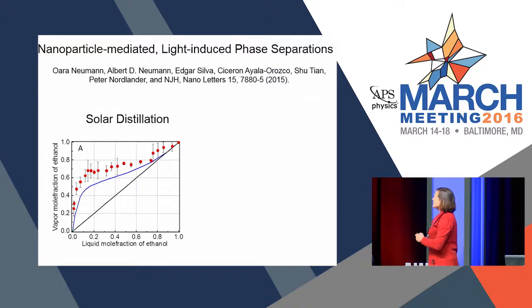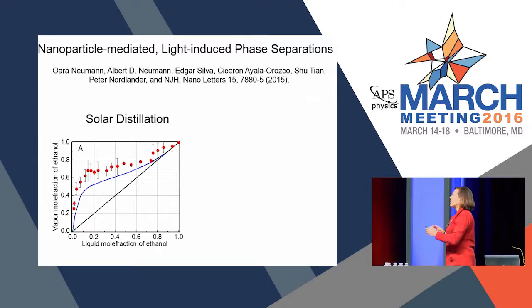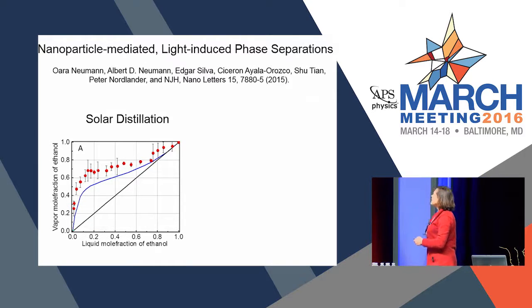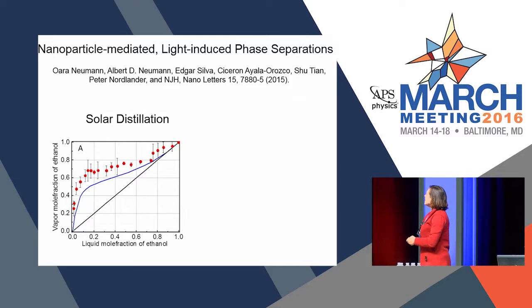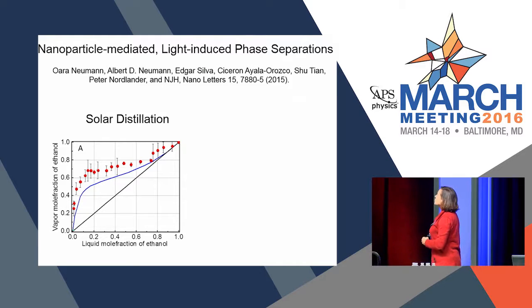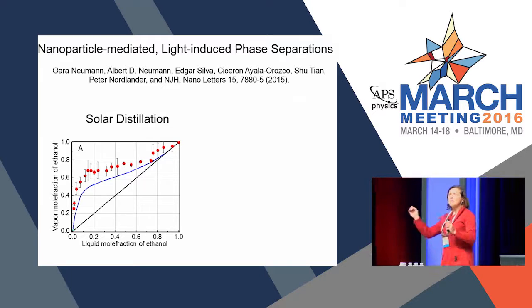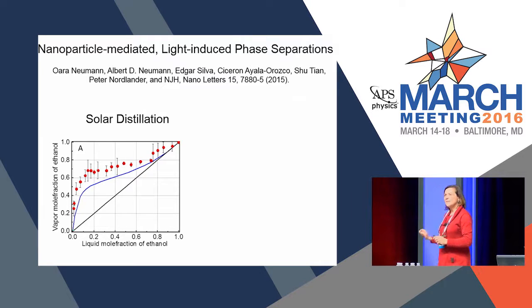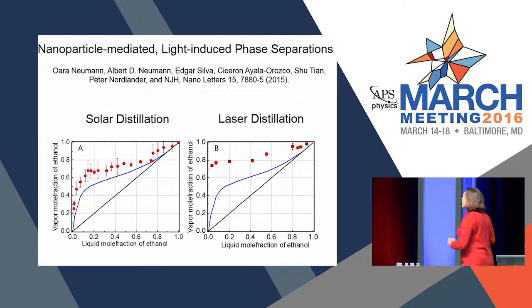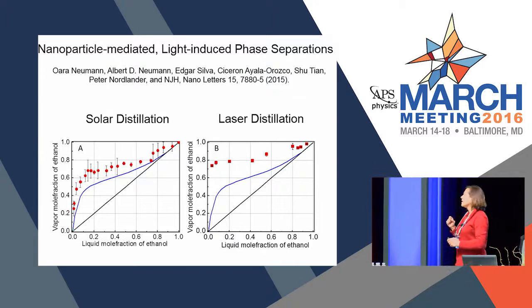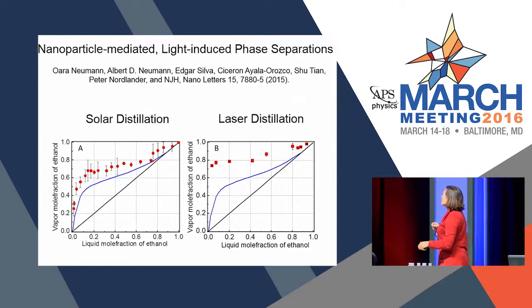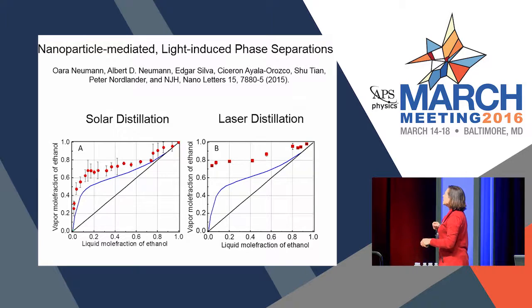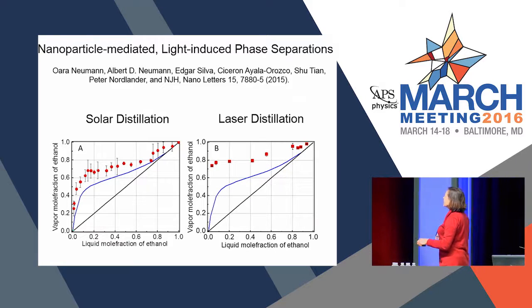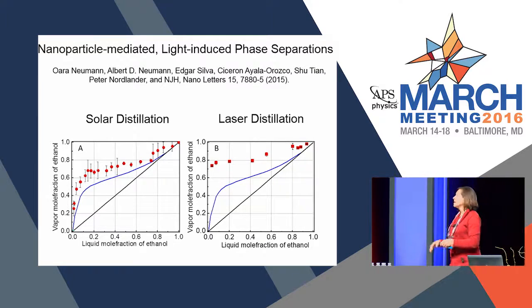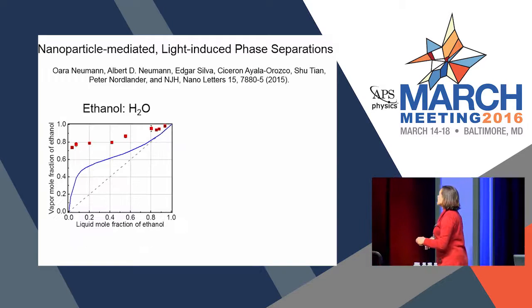And then at about 0.95 mole fraction, you can't distill any further, and you have what's called an azeotrope. So we saw this very unusual distillation curve, but it was also very noisy because we did this experiment outside. We have to go inside, do it in a clean environment, and what we find, in fact, is that we have an extraordinarily clean way of distillation, and we actually have 0 azeotrope in the case of a water ethanol distillation.